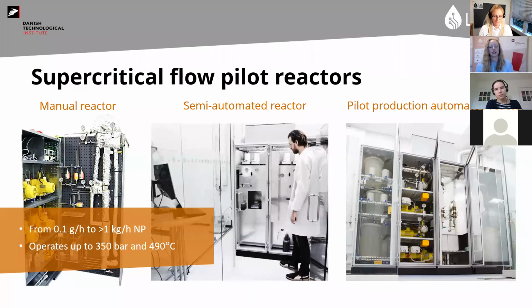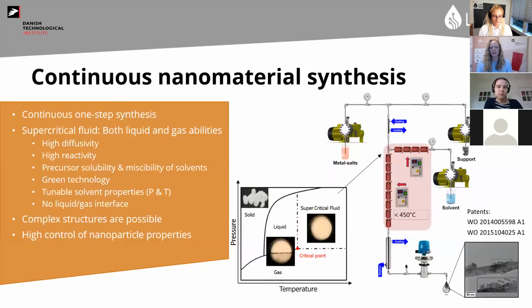So we are up around 350 bars and 490 degrees. And the way it works is that we have a continuous flow. So if you look at the schematic of the reactor, we can have a metal salt, for example, silver nitrate, in one of the pumps, the one where it's metal salts. And then in the other pump, that's a support, we can either have another metal salt or we can have a support material. For example, it could be carbon. So we want to produce silver on carbon in this case.